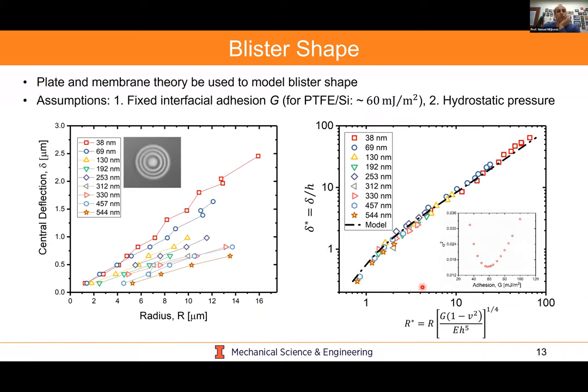So the first thing we did is we looked at the blister shape and how these blisters grow and what they look like. What I'm plotting here is the central deflection of the blister. This delta is the distance at the center from the tip of the blister to the substrate itself. So think of this as a small hill, and the height of the hill is what I'm plotting here. This is for a variable number of coating thicknesses, so these different lines represent different coating thicknesses. And this is the height as a function of the radius of the blister. And you can see these basically linear behaviors form.